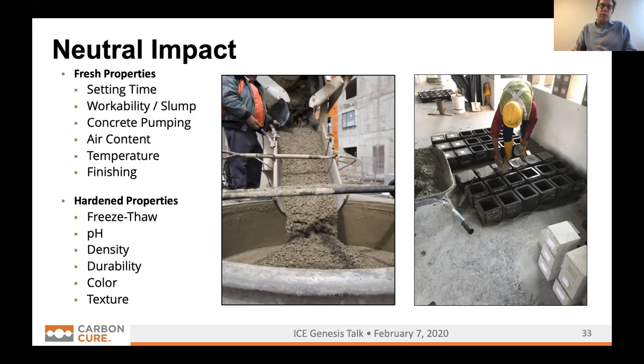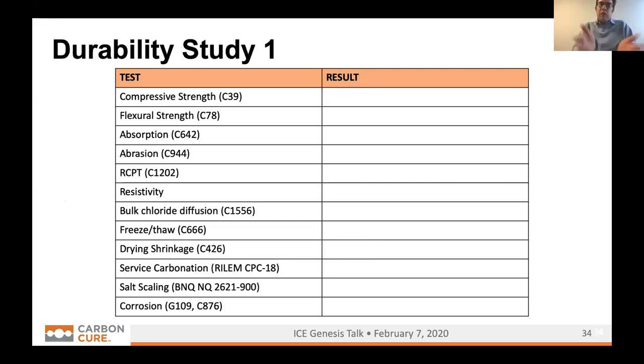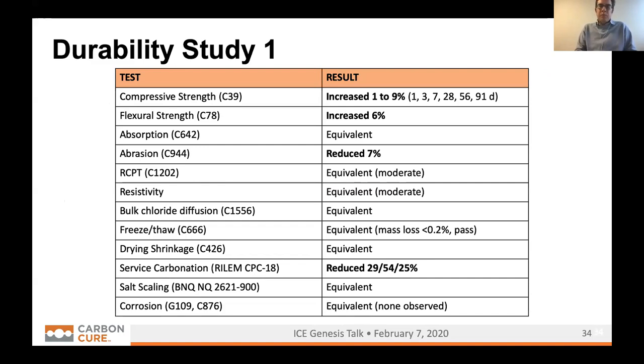Furthermore, once the concrete has been produced, for the hardened properties we have not collected any data or feedback that raises any concerns. This tiny amount of CO2 added to the concrete does nothing to the freeze thaw, does nothing to the concrete alkalinity or solution alkalinity. The density and color and texture of the concrete have not changed. So if we talk specifically about the durability tests, these are ASTM standards, C standards, with the exception of the RILEM tests. But these are industry accepted standards for testing concrete durability. And if we look at the results, in this particular case, you're doing a very small comparison of small data sets.